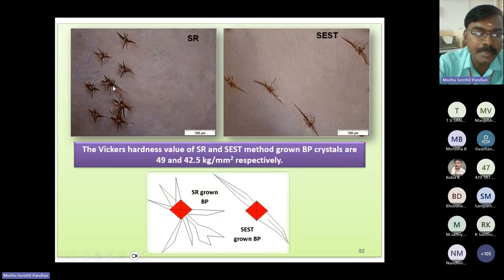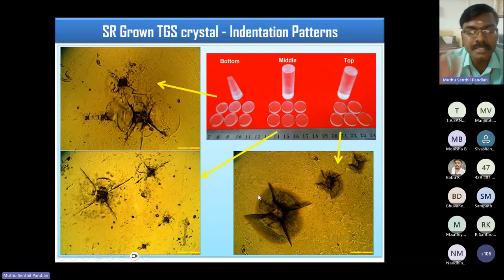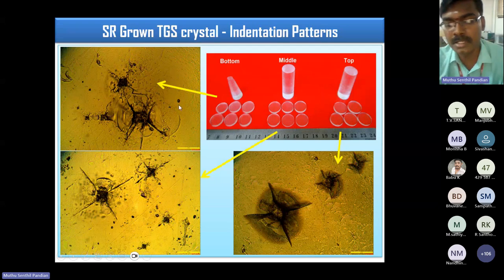And the number of microcracks produced near the indentation is very high in the SR method grown crystal compared to the conventional method grown crystal because of the higher mechanical stability. So more microcracks appear near the indentation in the SR method grown crystal compared to the conventional method grown crystal. So this is the 25 centimeter longest TGS crystal. To check the homogeneity of this SR method grown crystal, we selected the bottom, middle, and top portions and checked the Vickers microhardness number. The Vickers microhardness number at the bottom, middle, and top portions for the SR method grown TGS crystal is more or less similar.